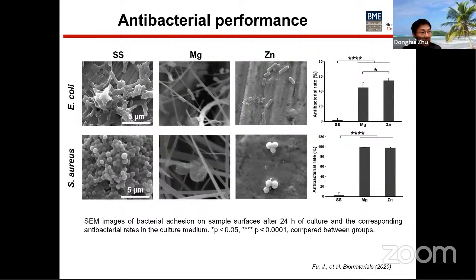Another good thing about magnesium and zinc material is their antibacterial property. For example, on stainless steel, both E. coli and S. aureus can form intense biofilm, while on the magnesium and zinc surface you see significantly less attachment of those bacterial strains. Their antibacterial rate is about 40 to 60 percentile in solution, and on the material surface it's almost 100% antibacterial rate.